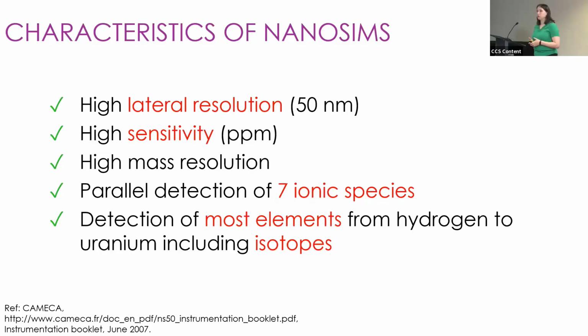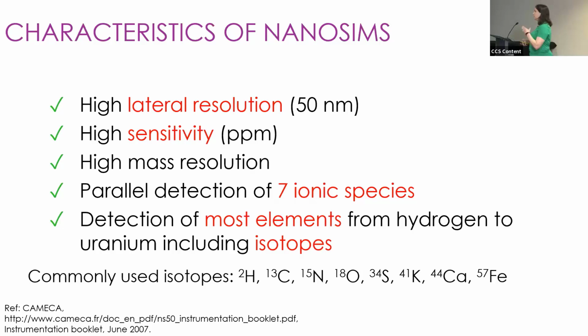The key thing for this talk is that the NanoSIMS can actually detect almost all elements in the periodic table, right through from hydrogen all the way through to uranium. There are very few techniques that can detect light elements such as hydrogen, lithium, and boron. The NanoSIMS is really good at that. And as I mentioned, we can detect isotopes. This is a mass spectrometry technique, so we can utilize this to artificially introduce isotopes into our sample and track where they are going. Some commonly used isotopes are listed here. In this presentation, I'm going to focus on deuterium especially, and also oxygen-18 and how we have utilized that.